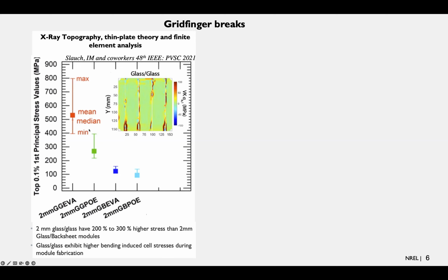And they saw, in terms of the top 0.1% of the first principal stress values, the very highest in the glass modules compared to, say, the glass backsheet modules. So there's a relationship between these two DuraMAT projects, whereas they did the modeling and some testing, we did the stress testing, and we can see the commonalities, which I thought was fairly interesting.